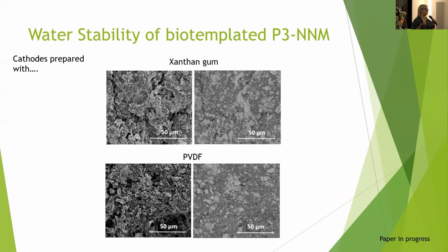I have secondary electron images and backscattered. So you can see a different contrast in these backscattered images. There are regions of more lightly colored areas, and that's my active material. So you can see I've got quite significant agglomeration in both of them. So these aren't forming because of the cathode preparation, but because of how I synthesize my material and the fact that they are fairly nanosized.